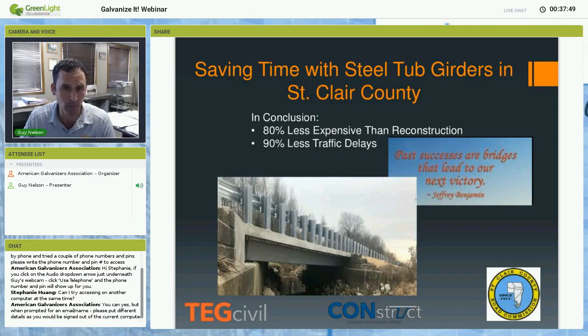And really, we did it with 90% less traffic days. Again, that assumes about a 4-month typical closure to do a full reconstruct of a bridge. Typically, in a Michigan winter, we have about 4 months to get in and get out before winter.